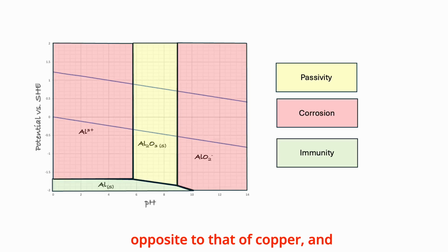Aluminum exhibits behavior opposite to that of copper and somewhat similar to zinc, except that the immunity region for aluminum is at much lower potentials. With respect to pH, aluminum corrodes at both low and high pH levels, but remains passive in the intermediate range, where stable films can form on the surface. For aluminum, there is a consistently high driving force for both hydrogen evolution and oxygen reduction during corrosion across all pH levels, as the oxidation lines for aluminum are substantially lower than those for hydrogen evolution and oxygen reduction.